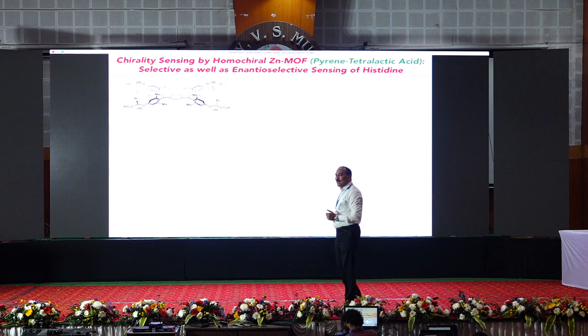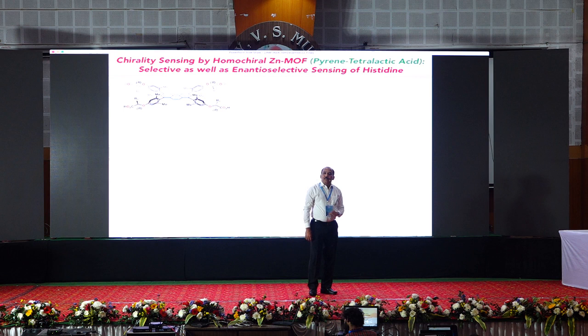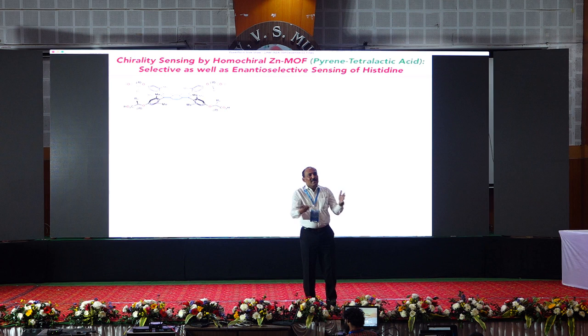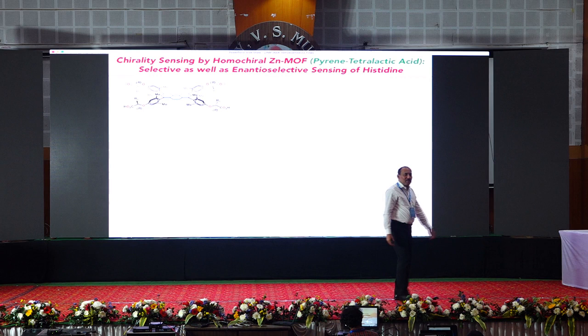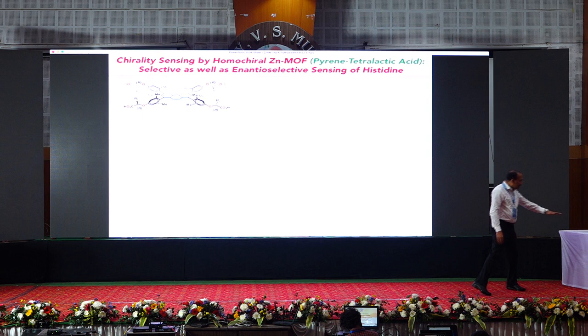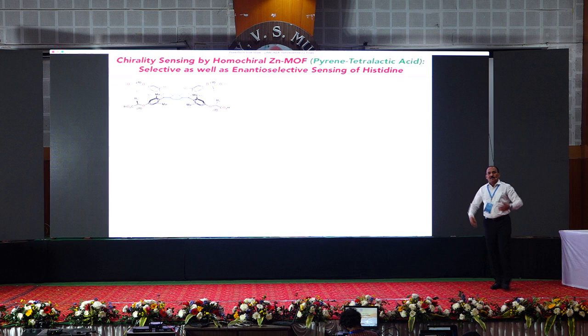So let me take this particular case. Pyrene, right, is a flat molecule, like a table top. But pyrenes stack on each other in the solid state. And when there is stacking, it's a brilliantly fluorescent material, but there is a concept called self-quenching. You shine light, the fluorescence is quenched, and you don't have the fluorescence. The quenching happens because of the stacking. So we can worry about preventing this stacking, and here you have a tabletop, I can do the paneling. So if I have a panel here at the four corners, like rigid panels, then molecules cannot come together.